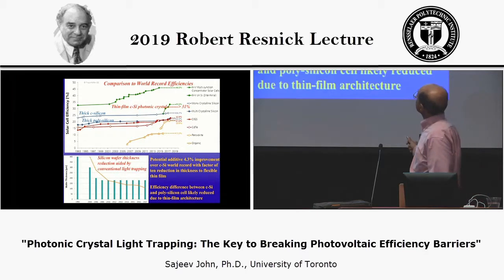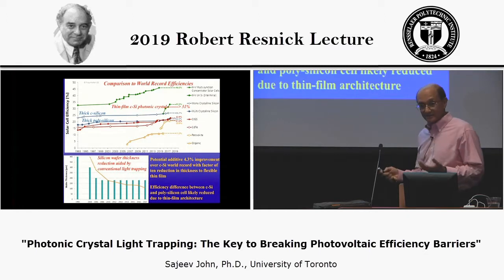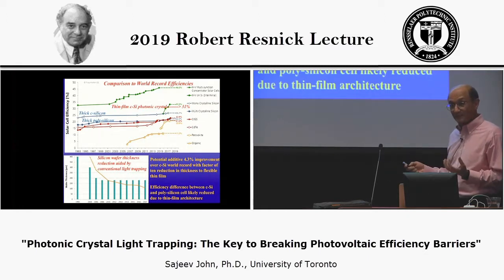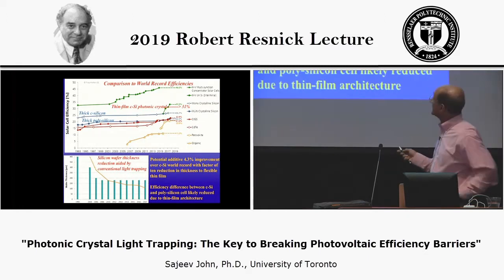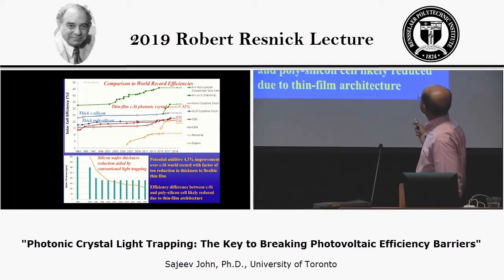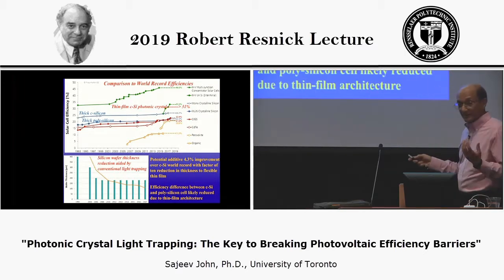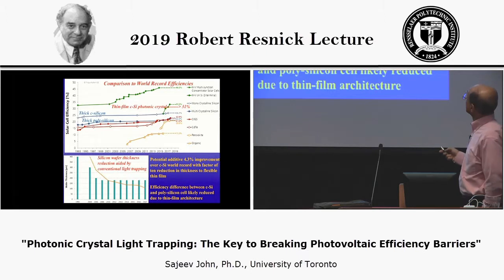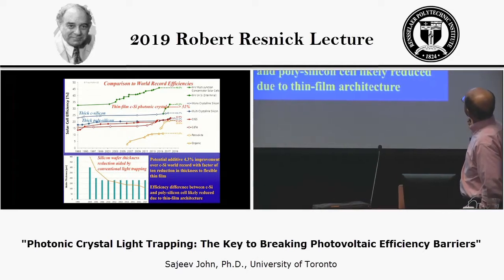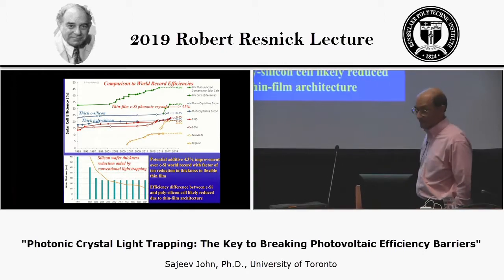What we're suggesting is that with thin film crystalline silicon architectured in the form of a suitable optimized photonic crystal, these inverted pyramid structures, we should be able to achieve at least a theoretical efficiency of 31%, which would be higher even than the best gallium arsenide solar cell that has been made, and very close to that of some of these multi-junction cells. The next curve above it is a III-V material on top of silicon, which has shown 33% efficiency.